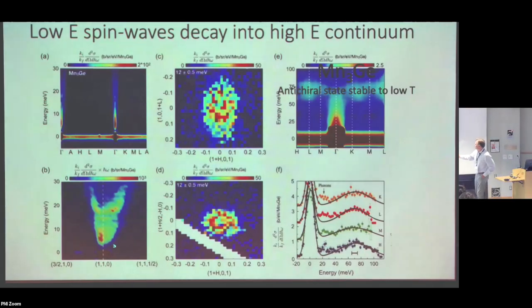Basically, in this plot, these are two different directions in momentum space. One is in the plane, the other is out of the plane, and you have pretty much the same steepness of these curves, and that directly shows that the spin wave velocity is quite similar in the two directions, so there are quite strong interactions out of the plane.